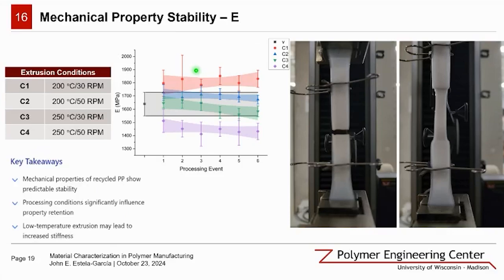So we observed that lower temperatures in extrusion can lead to increased stiffness in our recycled material. And this finding has important implications for recycling processes when it comes to maintaining or modifying mechanical properties. The predictable nature of these property changes is valuable for manufacturers. It allows us for more accurate forecasting when it comes to material performance over multiple recycling cycles, potentially extending the usable life of a polymer.